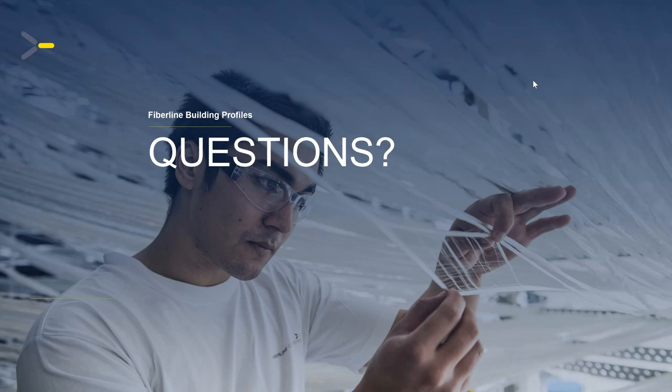Yes, very good question. The only viable way of recycling GRP today, economically speaking, is what we call the cement clinker route. What we do with our scrap in the production is send it to a company which shreds the big profiles into small particle-sized parts. Those small parts are then used in the production of cement. Those particles consist of fiberglass and resin. The resin is used as a fuel for the cement production, and the glass, which is silicate, is used as an additive for the cement production.